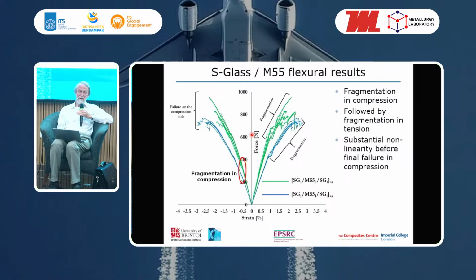Then we go higher, and at this point here, at about 1% in tension, it starts to fragment in tension. So now we see much more change in the slope and more damage because it's fragmenting in tension as well as the compression that we saw down here. And eventually we get up to quite a high strain here and we get a catastrophic delamination.